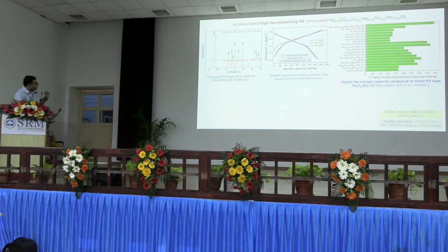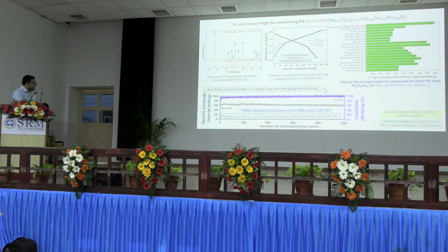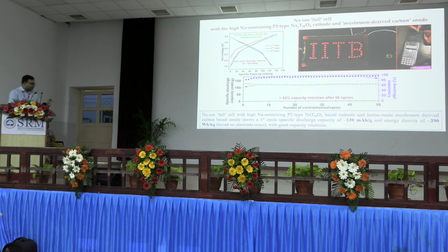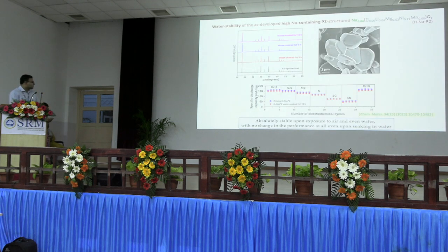And we could achieve a phase pure P2 type structure, and this material is now very easy to make, and the performance is also good. This is a high sodium containing P2 structure layer transition metal oxide, so the performance is very good. Between 2 to 4 volt we get a discharge capacity of close to 150 milliampere hour per gram, and the cyclic stability is excellent. So this is a very good material even from a practical perspective. It's a full cell, I don't want to talk much about it. And going by the group's theme, this is also water stable, because due to high sodium content, my interslab spacing is a bit sharp, so the spontaneous desodiation does not take place. Now we are making aqueous process cathodes also using this.